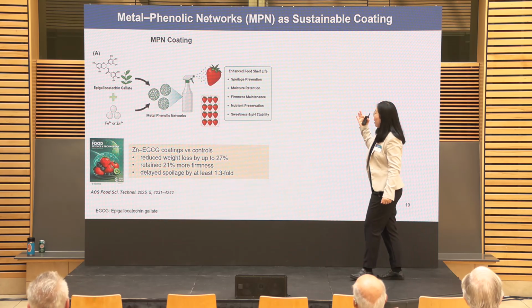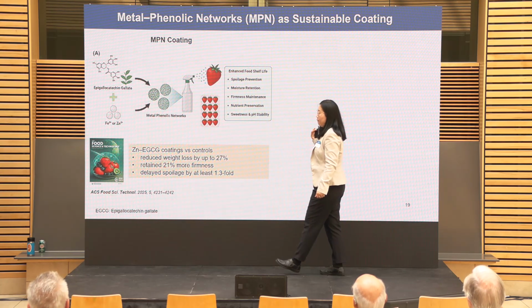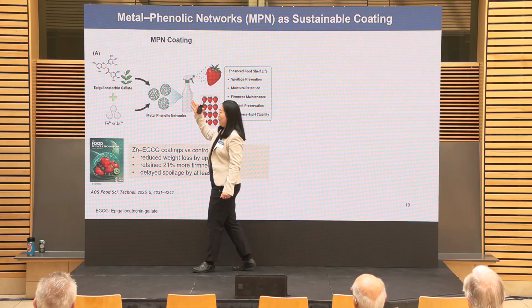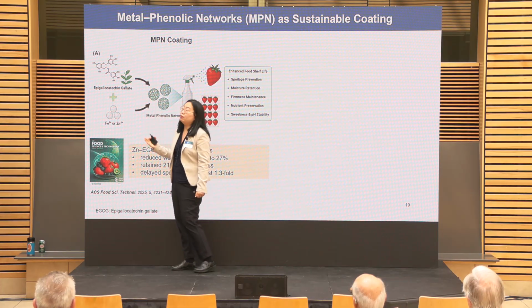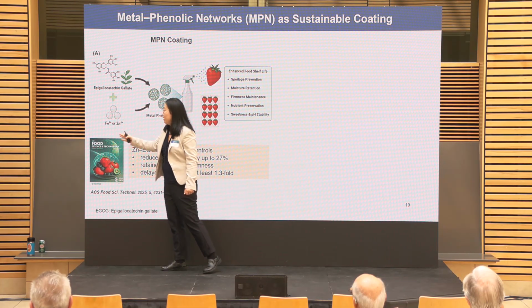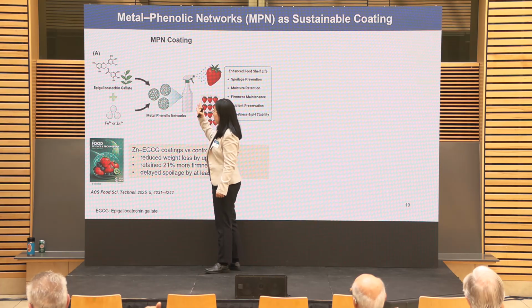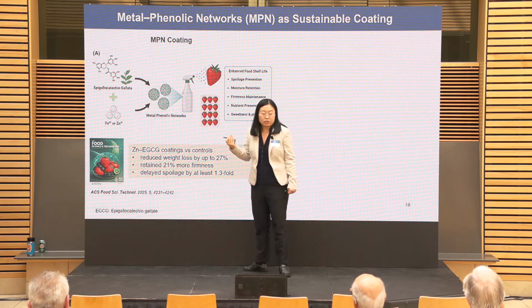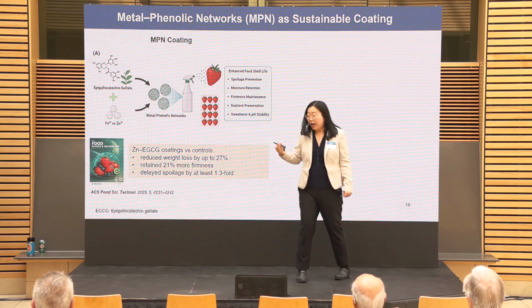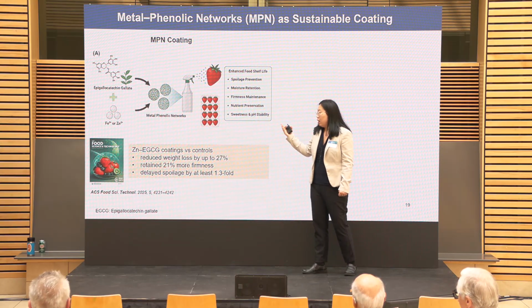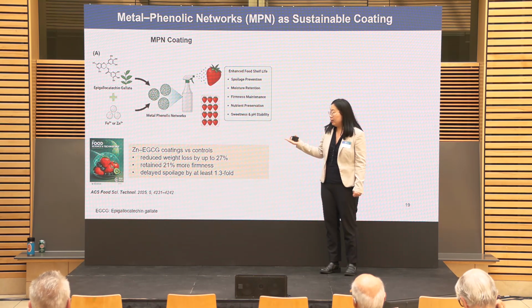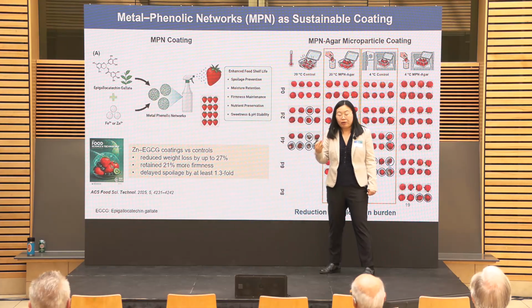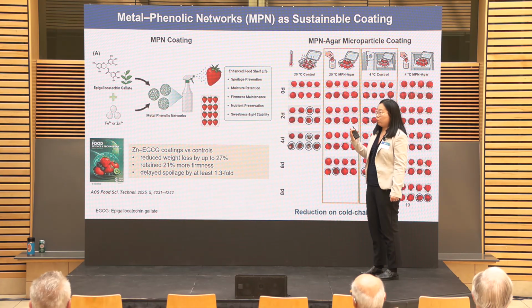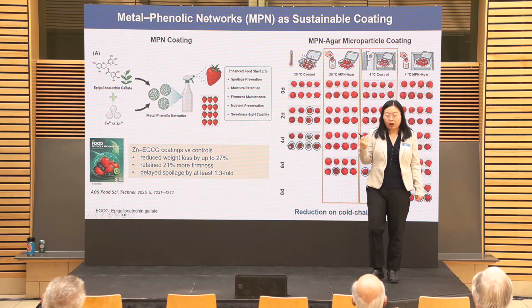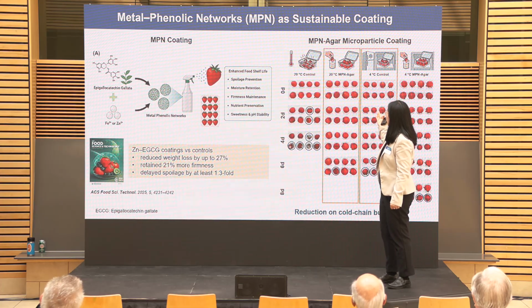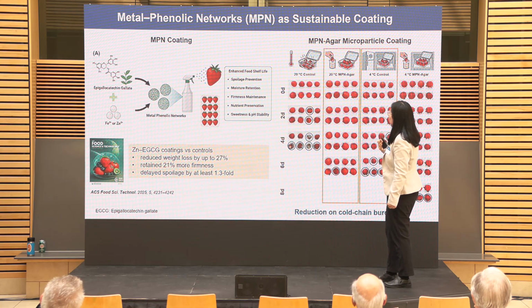So here is one example. We developed EGCG, which is a common polyphenol extracted from green tea, coupled with iron or zinc oxide. These simple coatings can extend the shelf life of fresh produce, and they can reduce the weight loss, retain more firmness, and delay the spoilage. And we further developed MPN coupled with the plant-based biopolymer agar to make MPN agar microparticle coatings.